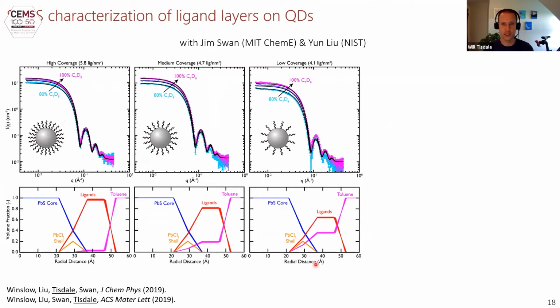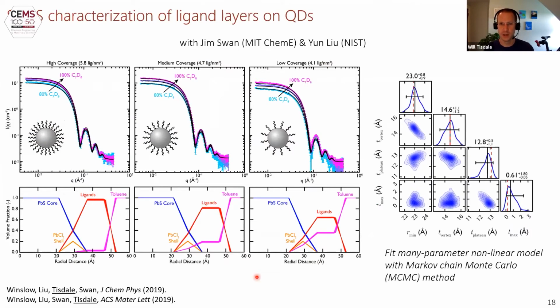And you can see that we have different concentrations of ligands, which was a proof of principle that verified our proton NMR experiments. One of the things that Sam and Jim have been doing that's particularly innovative is using robust Bayesian inference methods to get really statistically meaningful parameter distributions. So we've been fitting a many-parameter nonlinear model using Markov chain Monte Carlo sampling methods to get cross correlations between parameters, understand which two parameters are interchangeable and redundant with each other, and to get an overall sense of the parameter distribution.